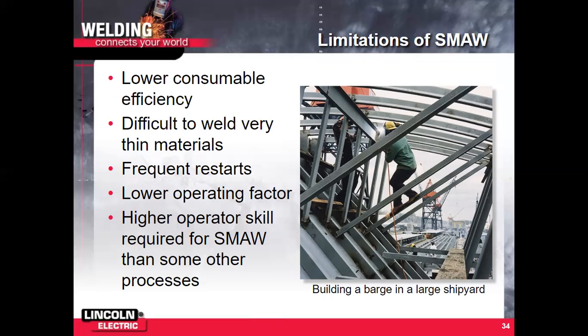But sometimes rods get damaged. So then you lose some rods. If they're taking in moisture when they shouldn't be, that's not a good thing. You get a rod stuck, you break it off, you're kind of wasting a bit of rod there. Overall, generally, you get about 70% efficiency, 75% efficiency with shielded metal arc welding. Some people can run it more than that. Some people run it less than that.